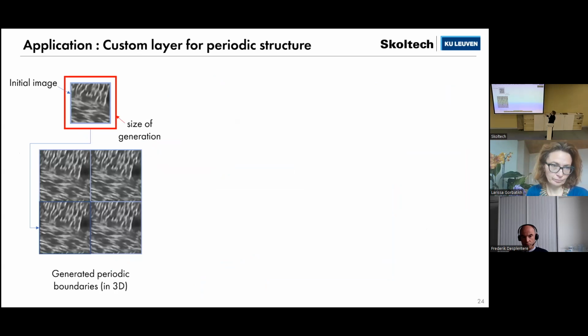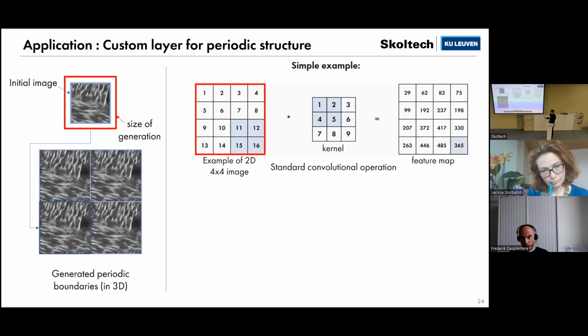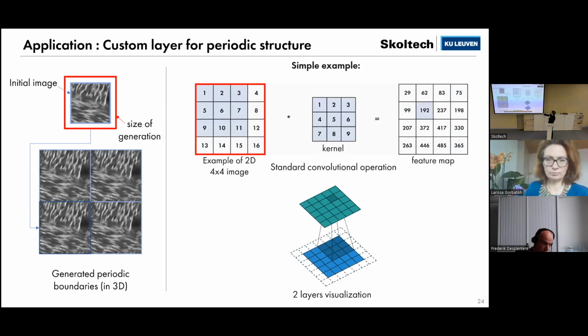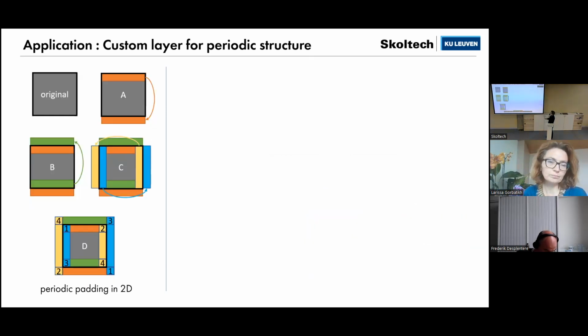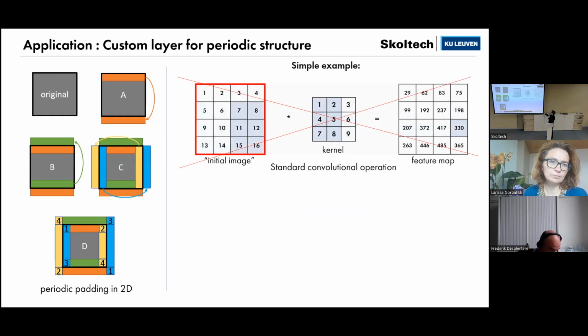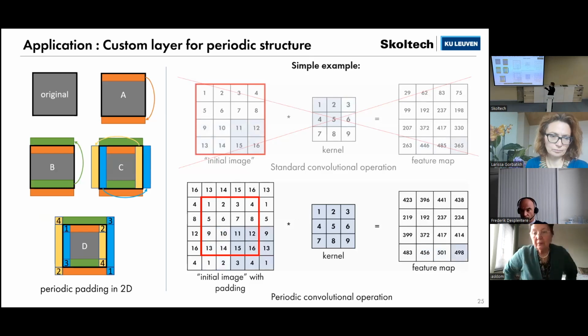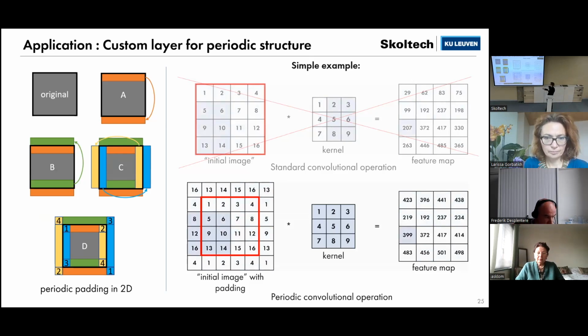We use periodic padding. So to briefly explain these custom layers, I will explain it on a very simple example of a 4x4 image. So here you can see how convolution works on the boundaries. On the boundaries, it just ignores some parts of the image and doesn't use the kernel at full size and generates this kind of feature map as a result. But yeah, here you can see how it ignores, for example, these parts as well. And of course, everything is done in three-dimensional space. And if we implement periodic padding, we will not need to use these standard convolution operations, and we will use the same convolution operations, but on the boundaries it will use the kernel at its full size without these large property jumps on the border.